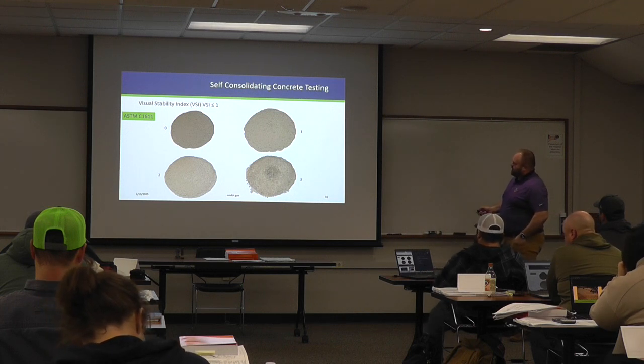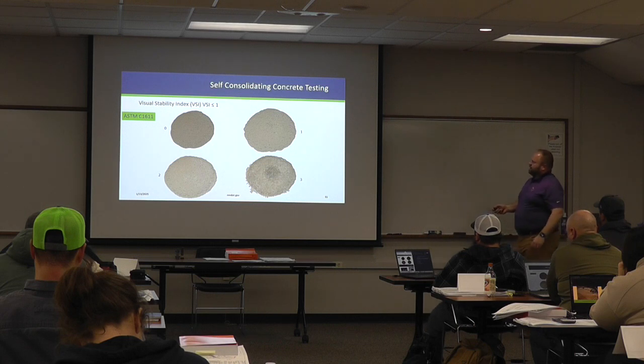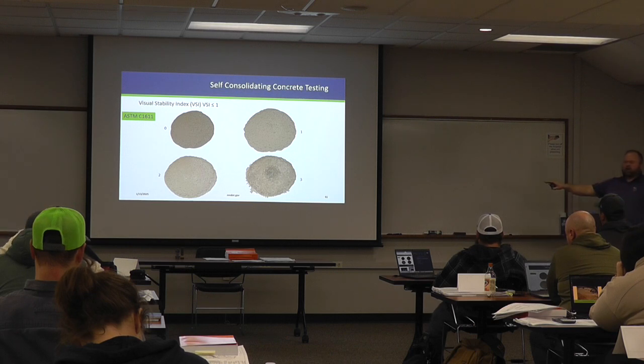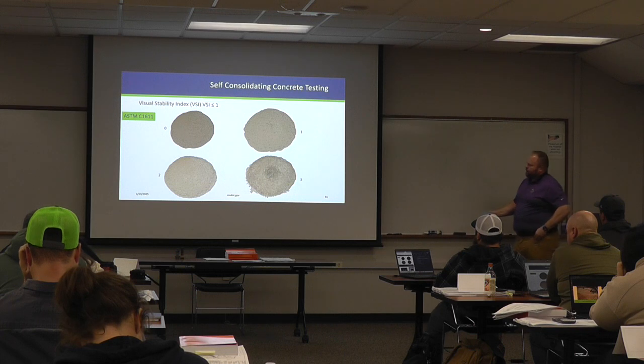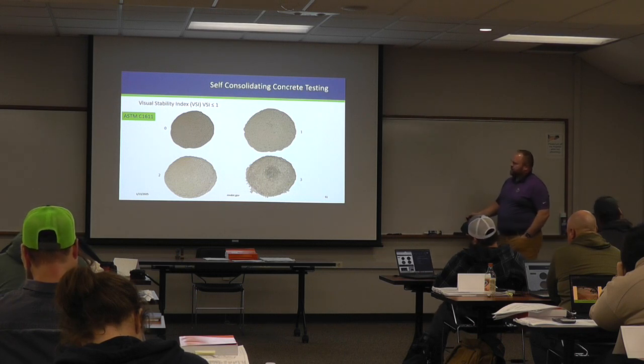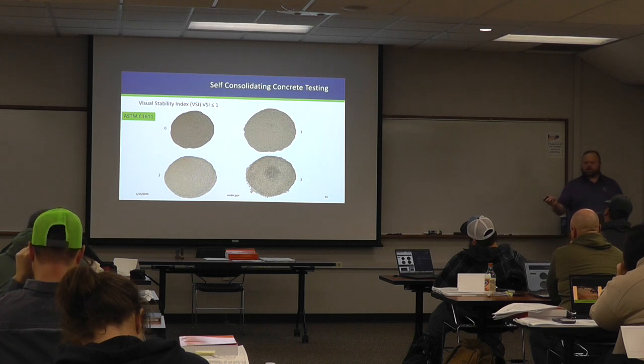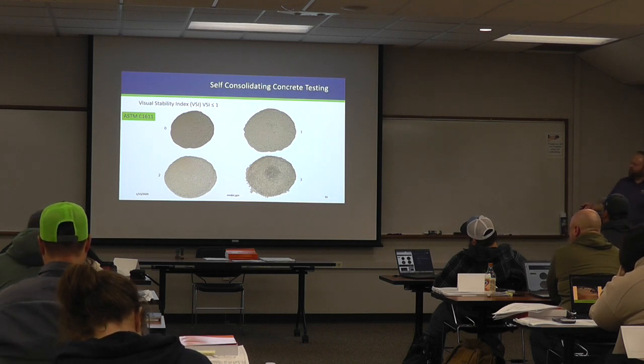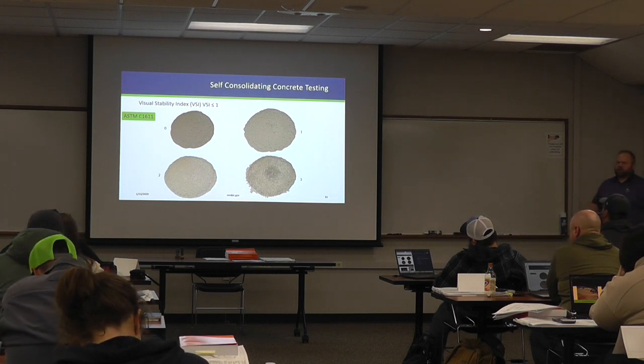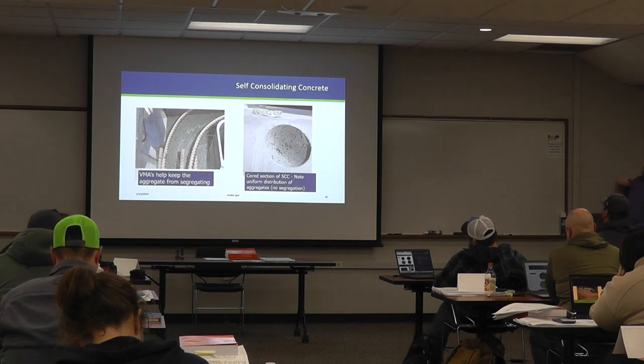But then if you look at 3 here, we've got aggregate that if you were to tip this up and look at it from the side view here, you might see like a little mound of that coarse aggregate. That's obviously not spreading out with everything, so that would be a 3. And we also got a little bit more of that bleed that's coming out of the edge of the pancake there. I think our spec used to be 1 or less, and I think it's 2 or less now for our SCC when we're doing a visual stability index rating. But if you have a good SCC mix, it works really well.